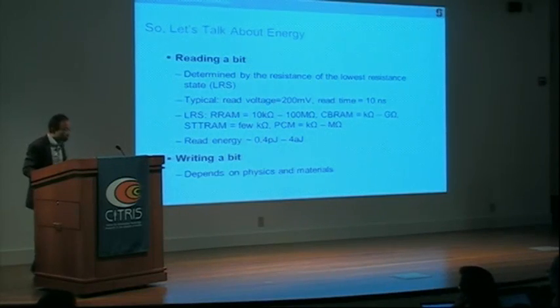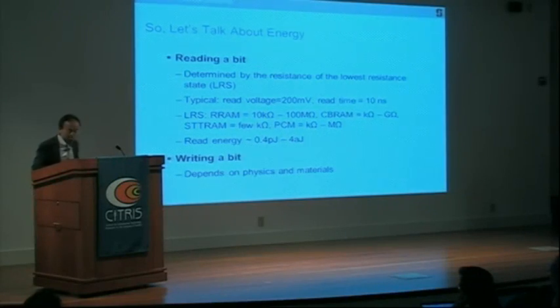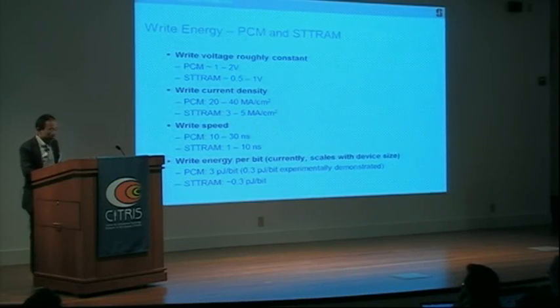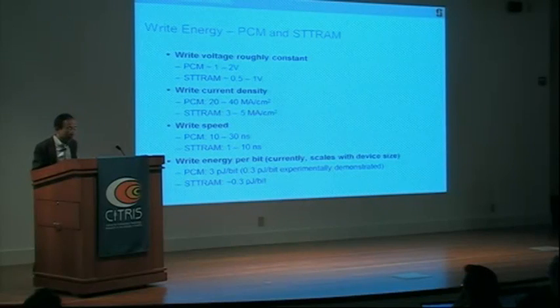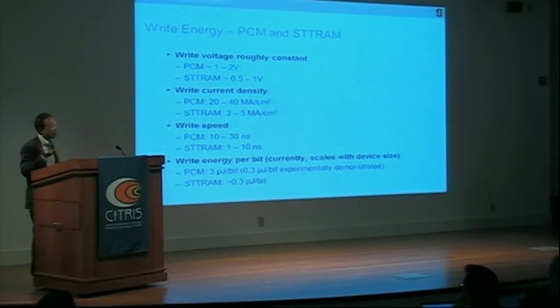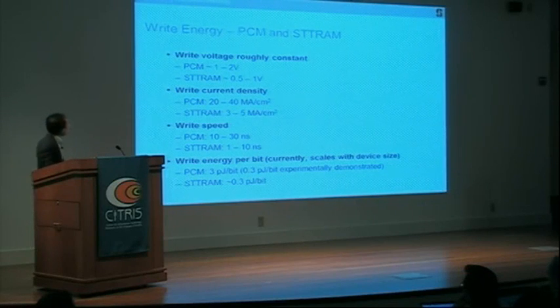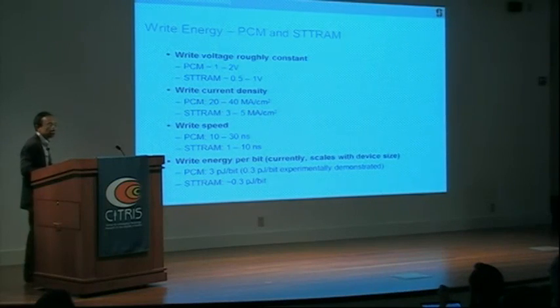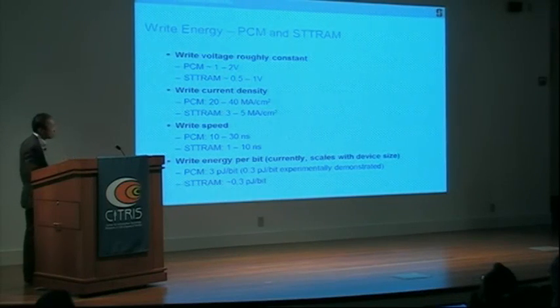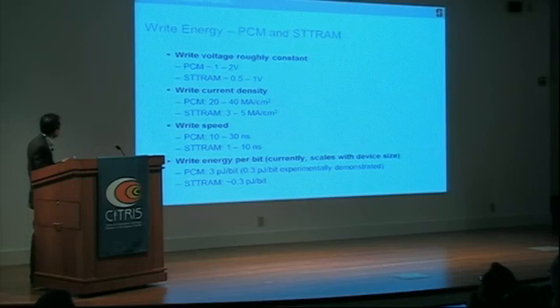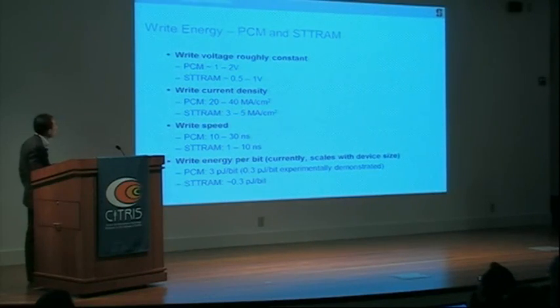Okay. Now, writing the bit depends on the physics and the materials, so you need to split the discussion in two. Let's talk about write energy for phase change memory and STT-RAM. Both of these work on current density, so they scale with the area. The write voltage for phase change memory is roughly constant because of the physics of the electronic switching, which tends to be anywhere from 1 to 2 volts. The STT-RAM switches at around half a volt to a volt. The write current density for phase change is about 20 to 40 megaamps per centimeter squared, while STT-RAM is about 3 to 5 megaamps per centimeter squared.